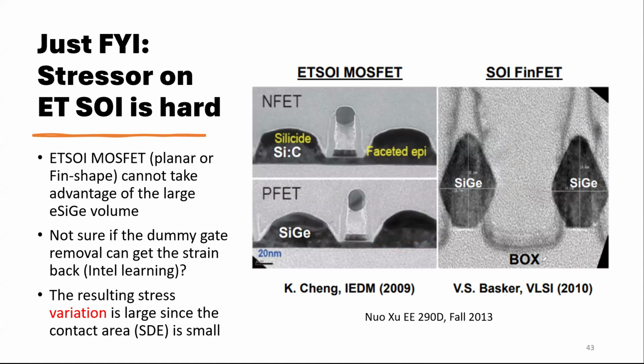Remember, this is the BOX, and then you have a different material on top. BOX as oxide has a very different crystal structure, right? The density is lower, and silicon is very dense. So naturally, the silicon on top, no matter how you form it, when you thin it down, will be highly strained by nature. And when you grow an epi from a strained, super thin substrate, you have problems. That's how nature works. I'm sorry. So 6, 7 nanometer, okay, but anything less than that, probably not.